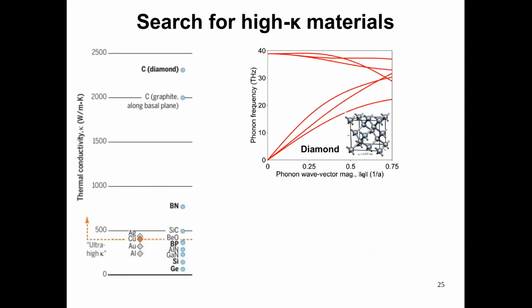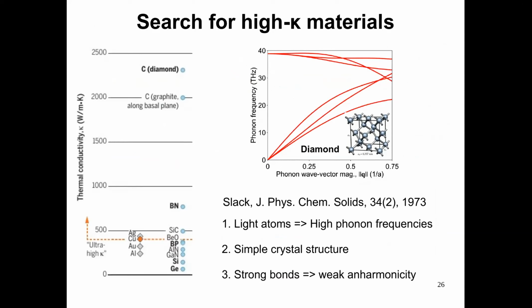So the reason to go beyond the conventional theory and really develop this unified first principles framework was driven by a need to find high thermal conductivity material candidates. As we all already know, diamond is the highest thermal conductivity material known to man. In fact, its thermal conductivity is more than 4 times higher than even metallic systems like copper and silver. So Glenn Slack in 1973 looked at all of these high thermal conductivity materials, that is materials which have thermal conductivity more than say 300 to 400. And he found several common features among these materials which give them the high thermal conductivity.